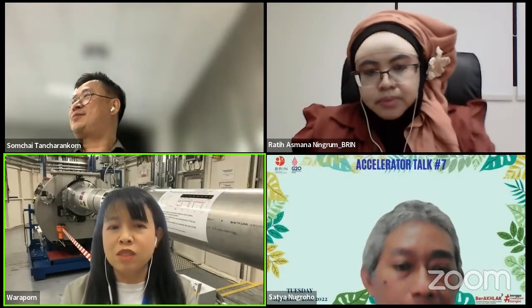For bulk property analysis, like XAS, X-ray absorption spectroscopy, or SAXS-WAXS, small angle X-ray scattering, you have to grind your sample to a powder first, and make it into a pellet, a 1 centimeter round pellet. So the sample preparation is crucial and has to be prepared accordingly, according to what you want to use for analysis.